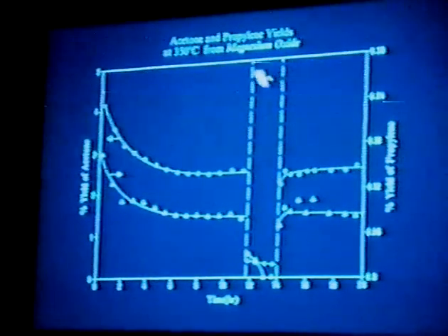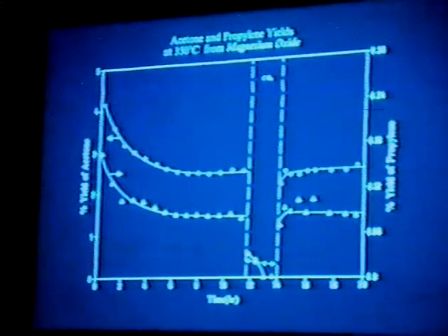We pulse CO2 at constant partial pressure of isopropanol, and in fact we do suppress both the propylene and the acetone formation. Remove the CO2, and we're back up to steady state. Again, it appears that the suggested mechanism is somewhat correct here.